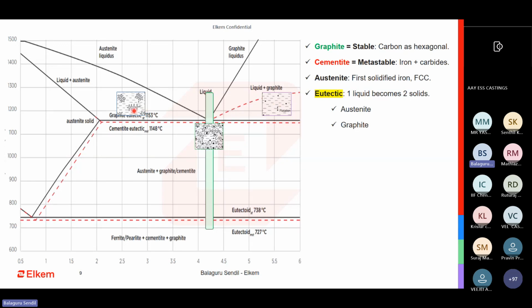It is very subtle changes, but if you are able to measure these changes and control them, then you can optimize your risering to bare minimum levels, which is the ideal zone in which we would like to operate. But most ductile iron foundries operate in the eutectic region of 4.3, where you have the transformation happening. The liquid is transforming into two solids simultaneously. So we have both the austenite and graphite growing. And then when it cools down further, the austenite interlinks together and forms a very nice microstructure.